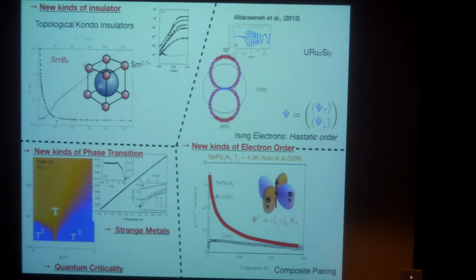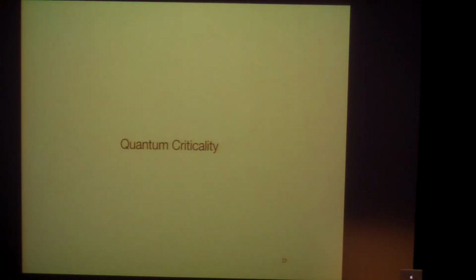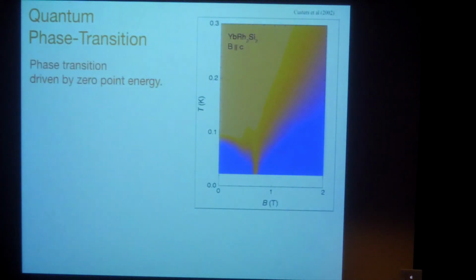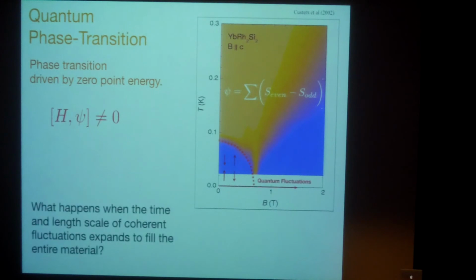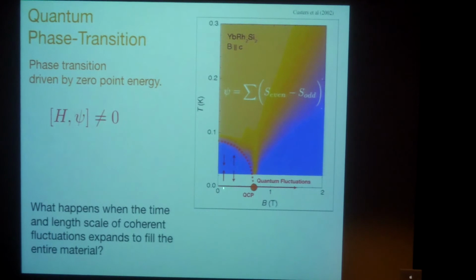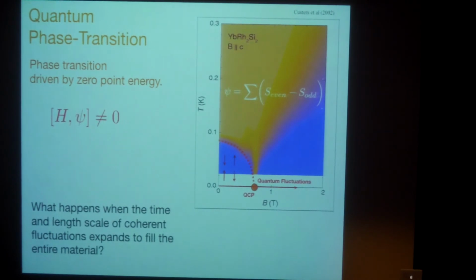Okay, good. So, let me tell you a tiny bit about quantum criticality and why it's still an unsolved problem and many people are trying to come up with new ideas. A quantum phase transition is a phase transition that occurs at 0 temperature driven by 0-point energy. And here is an example, ytterbium rhodium-2 silicon-2, which exhibits field-tuned criticality. If you cool it down at 90 millikelvin, it becomes antiferromagnetic, and the order parameter is a staggered magnetization. But as you increase the magnetic field, quantum fluctuations destroy the order and lead to a quantum critical point. Okay? So whilst we understand this transition, we don't understand this transition here, particularly in metals.